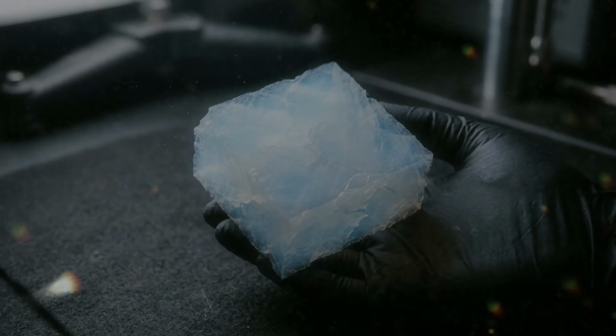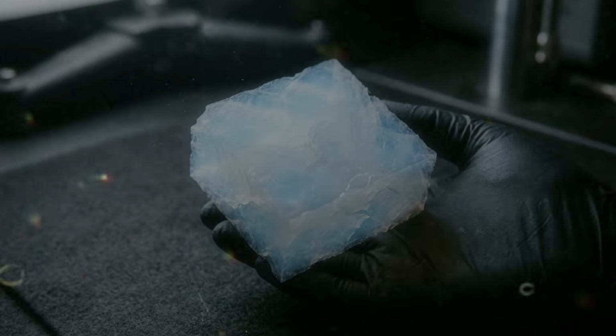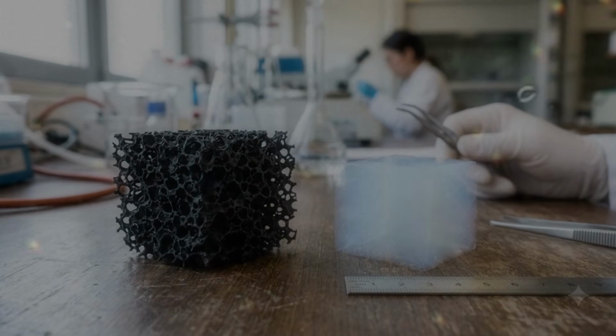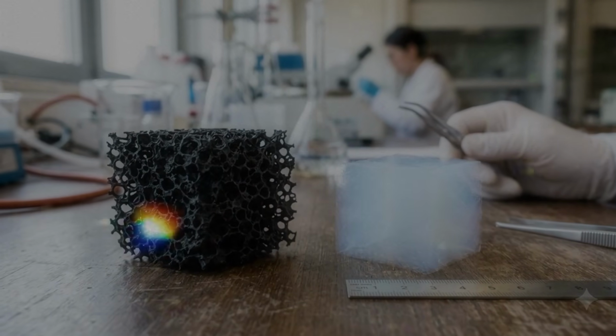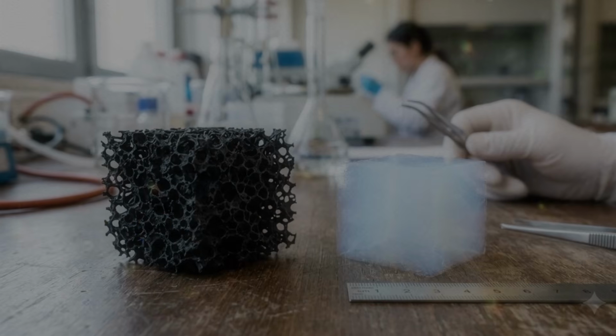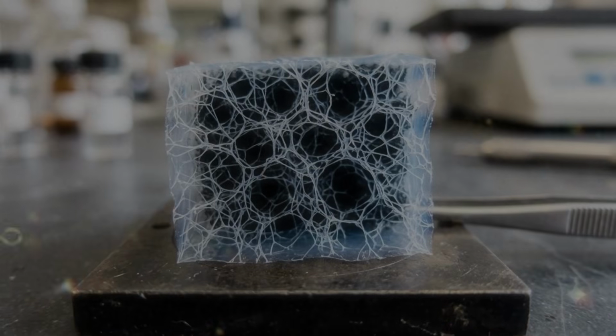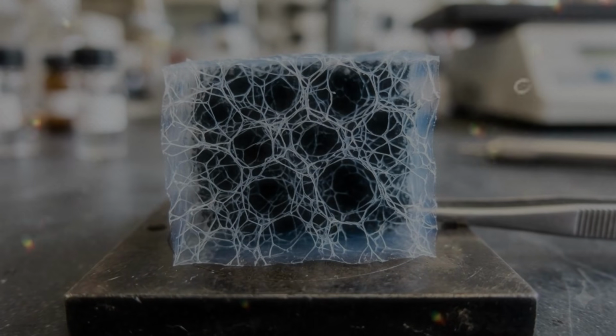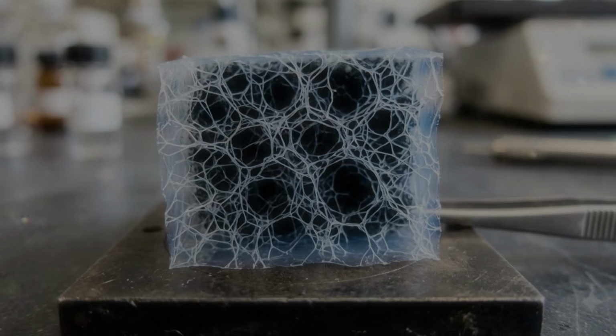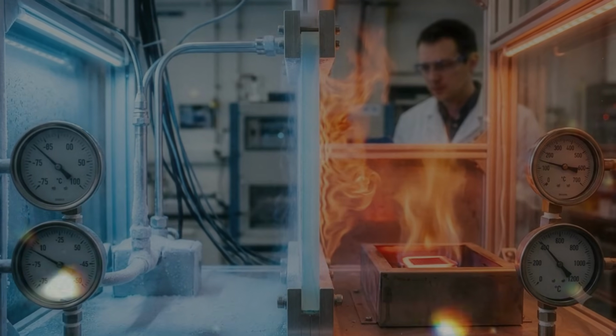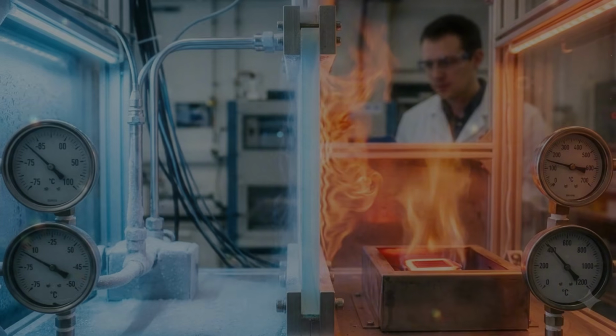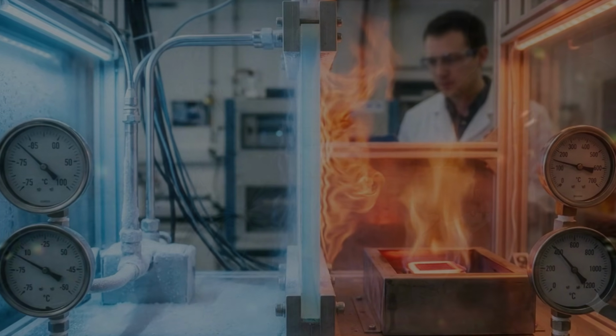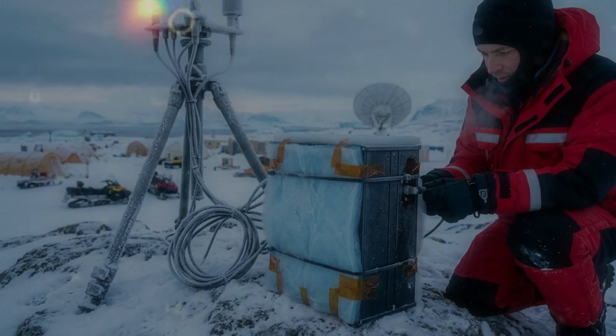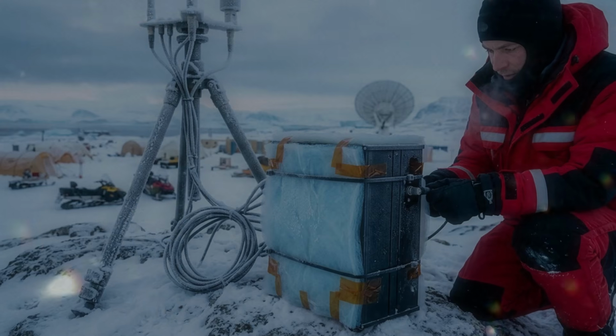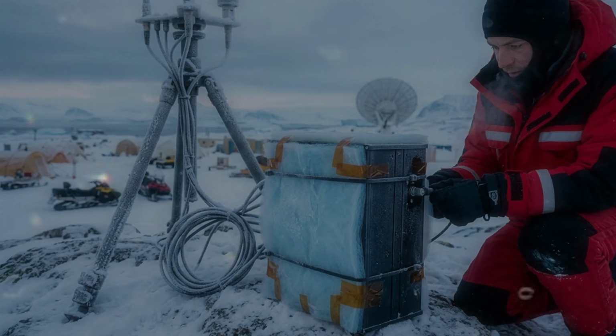The second problem is consistency. Graphene sheets vary in size, thickness, defects, and chemical composition. Different batches can produce different results. Standardized starting materials and processing methods will be needed. The third is integration. The aerogel must attach securely to metal contacts. It must remain stable in the electrolyte. It must tolerate repeated charging, heating, and expansion. A successful electrode is not simply a black sponge placed inside a battery.